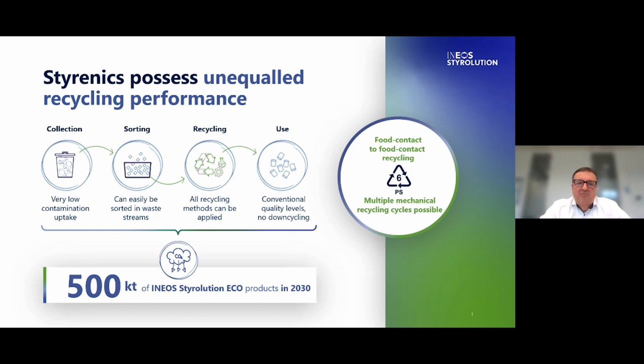Already in the collection phase, we see that styrenics, and here especially polystyrene, has very low contamination uptake, and I think that is very important to mention. That means the so-called cats and dogs that don't go into the polystyrene don't have to be removed later on, right? The next step, the sorting step, we see that by state-of-the-art technologies like near-infrared, it is very easy and very clear to detect polystyrene in waste streams. So it is definitely possible to combine the detection with sorting technologies to phase out polystyrene from the other waste. Recycling, I just mentioned, basically all recycling methods can be applied.